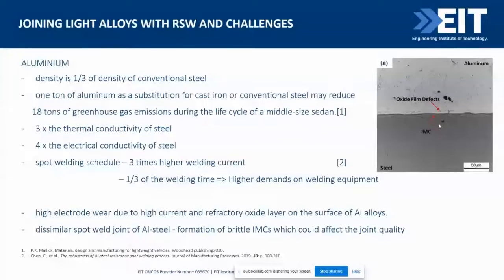When you weld them together, they create this intermediate layer, which we call the intermetallic compound, in short IMC. The IMCs are very hard and brittle. So again, when you pull the metal sheets, they can break easily. No doubt they are light in weight, but as you can see, with spot welding, the heating of the material changes the microstructure, and when it does, you're going to have issues like this. On top of that, magnesium as well as aluminium form oxide layers, and these oxide layers can easily stick to the welding electrodes. Again, that is another issue.